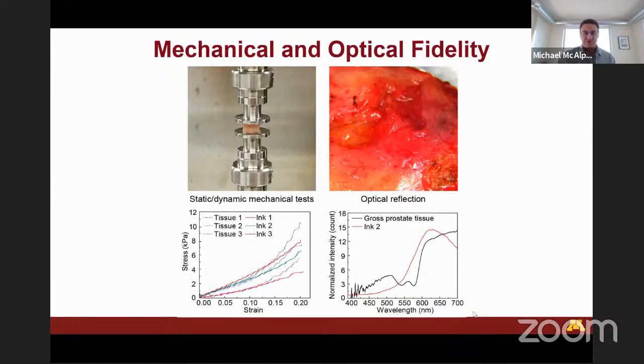And so we had those 3 tissue samples, and then we developed 3 inks that could be tuned so that they could basically mimic the mechanical properties of the tissue samples, as you can see, in the low strain regions. We don't yet have the ability to do strain stiffening behavior, but we're working on things like that. And then we can also replicate the color of these organ models by adding dyes.